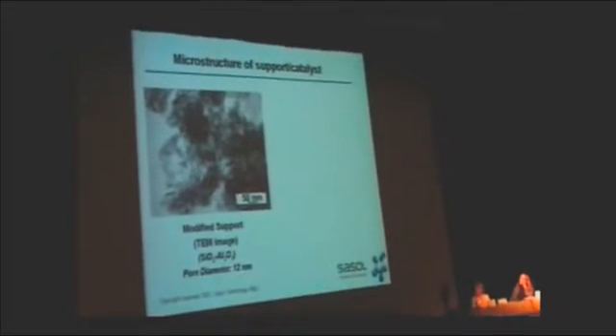On a microstructure level, the support that we've used in this study is the silica-modified gamma alumina, and it's made up of a lot of lamella, plate-like structures, which are randomly stacked to give you the pore structure in between with an average pore diameter of roughly 12 nanometers. During catalyst manufacture, you fill these pores with cobalt nitrate solution and following drying and calcination, you end up with a material looking like this.